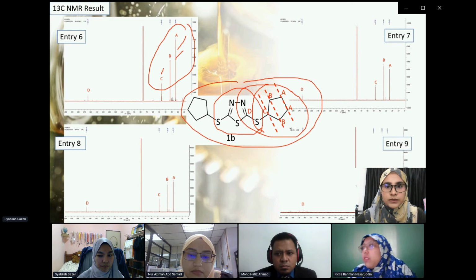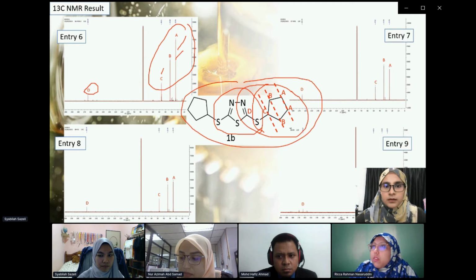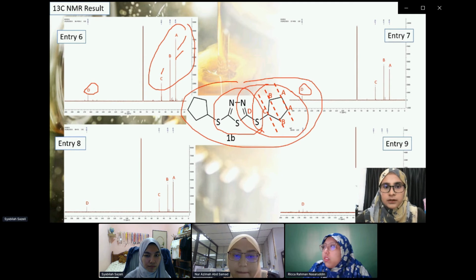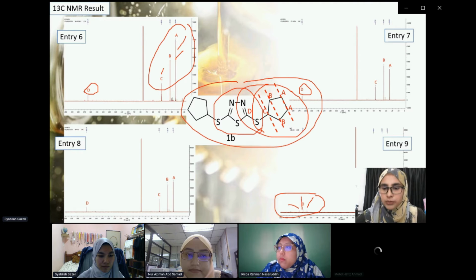For the aromatic side, the symmetrical sulfide shows only a low intensity carbon at peak D, while we expect to observe a double intensity peak for thiadiazole carbon due to the asymmetrical structure. Also for entry 9, there is a slightly different peak pattern, as you can see that there are 3 peaks at the D position. So this brings us into ongoing research.